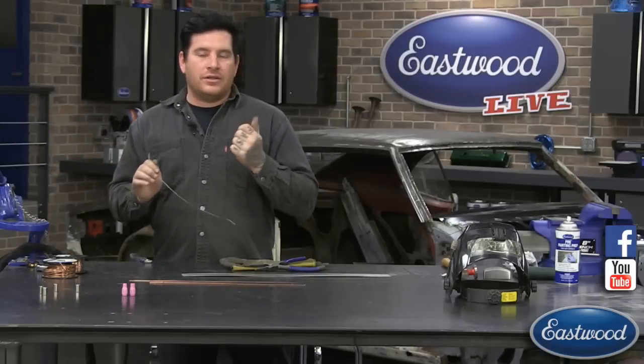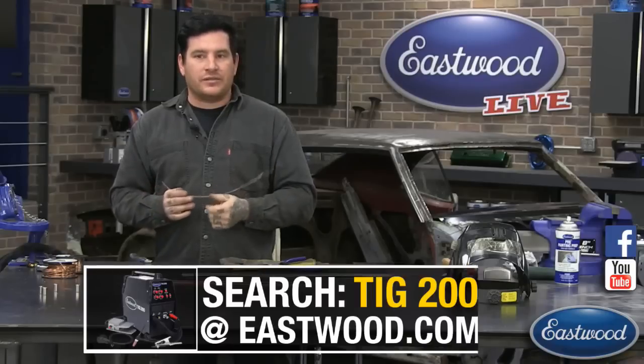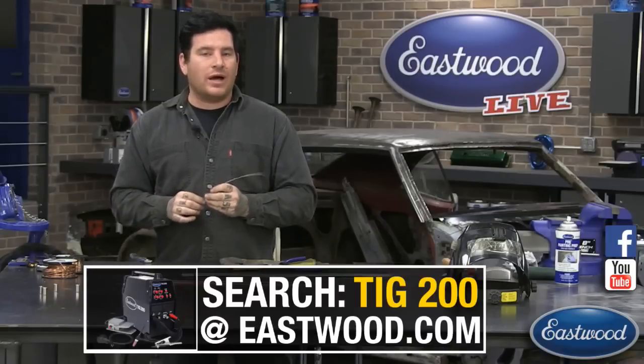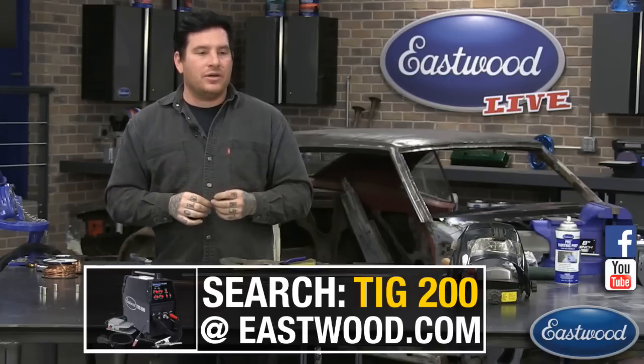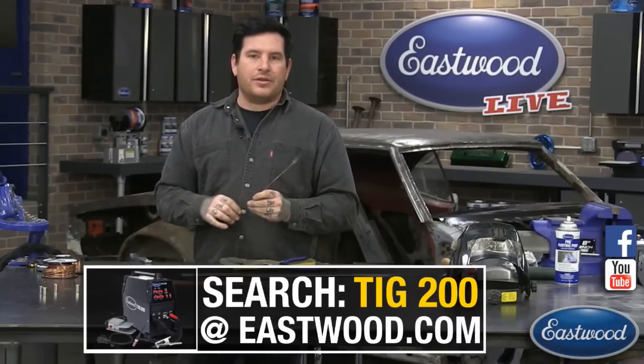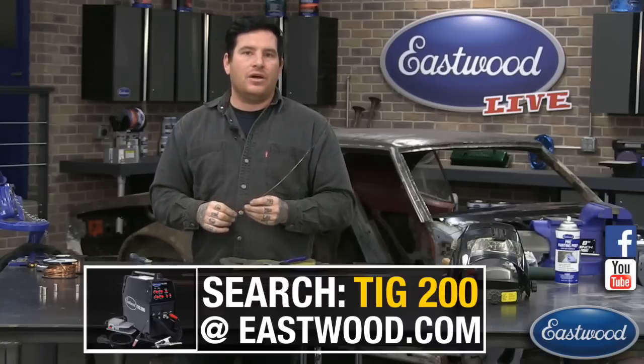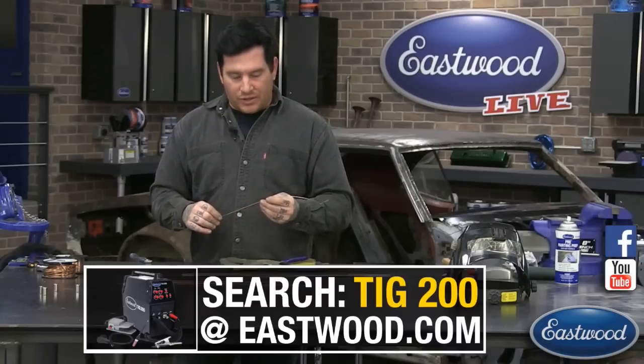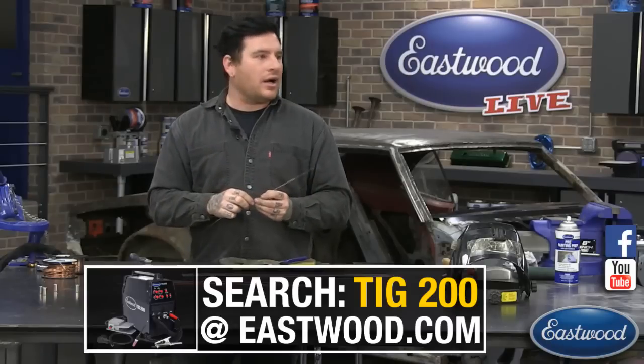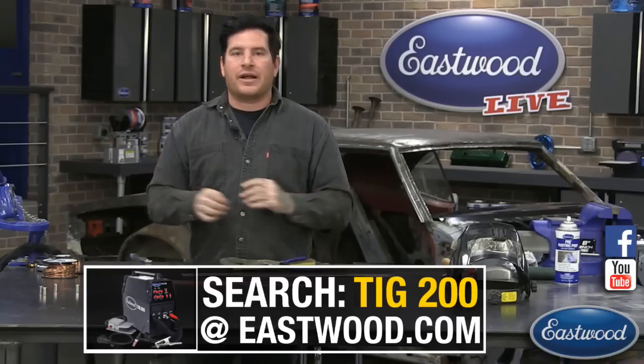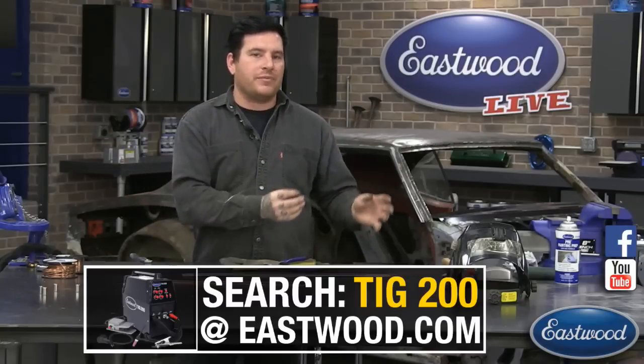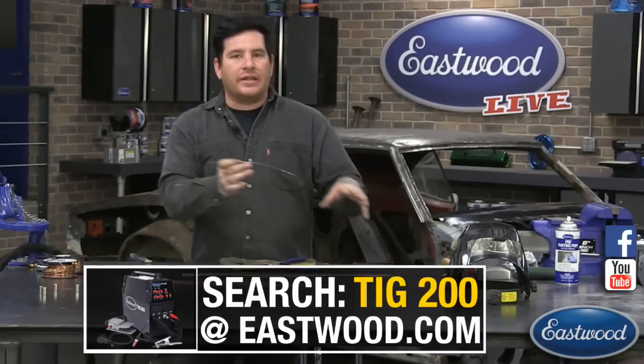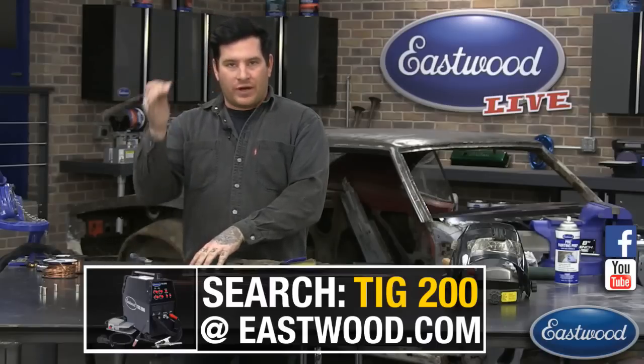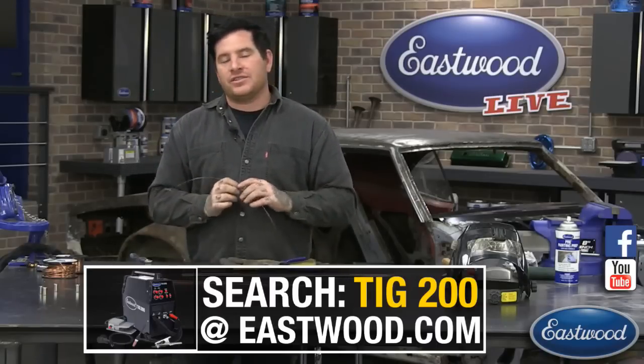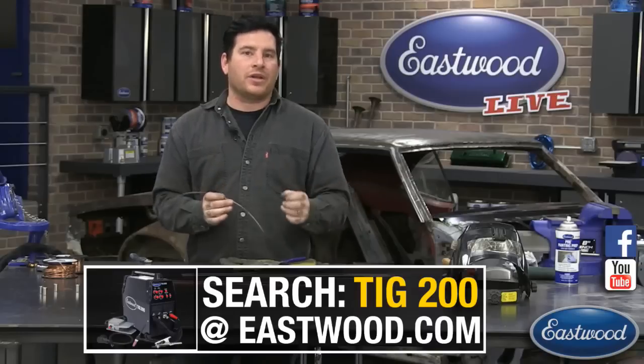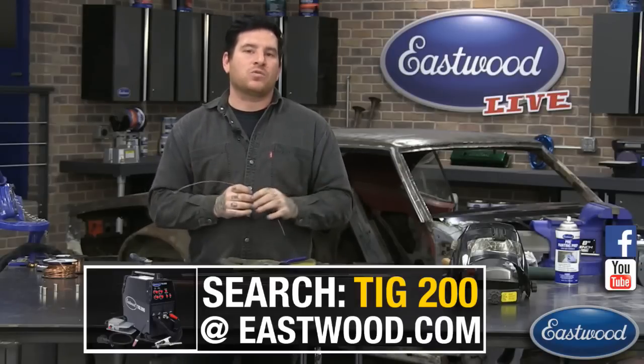It's all in the user. Are you up to the task skill level to weld it? And B, it's all in the preparation. Either the preheating and post-heating or cool down of cast iron, I'm assuming you mean cast iron, is very important. I don't care how good of a TIG welder you are, if you don't preheat the piece and let it cool down gradually and use the right filler rod and the right settings on your welder, it's going to crack. Your technique can be good as far as the welding it, but all those other things come into play and that's where it starts to crack.